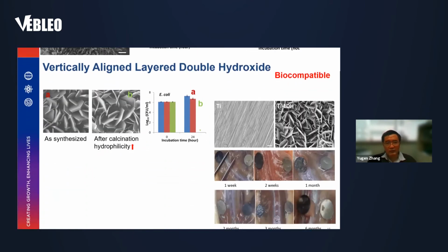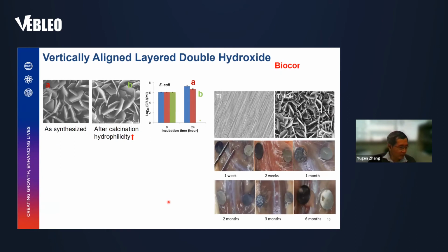Other than that, we're also looking for more biocompatible materials. And showing here is what we call vertically aligned layered double hydroxide, because this type of material has been widely used for implants. So it's a well-known biocompatible material. And here we grew this vertically aligned structure on different surfaces. And this is the as-synthesized structure, and this is after calcination. And actually, you can see after calcination, the structure becomes much thinner and sharper. And another important point is it becomes more hydrophilic.